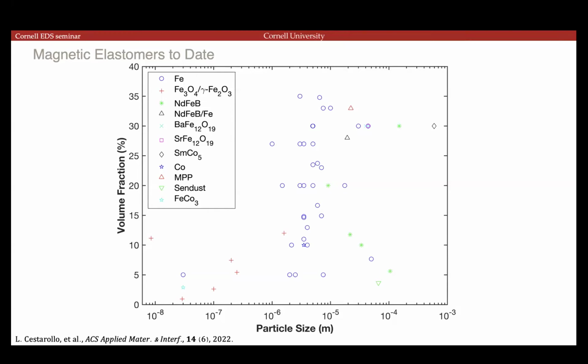Because they have a larger mass, generally when you try to apply a magnetic field, they have more inertia. So it'll take more magnetic field to move the same film if it has microparticles in it versus if it has something much smaller like nanoparticles. The drawback of nanoparticles is that if you scale them too small, they become thermally unstable and you lose all of your magnetization in general.